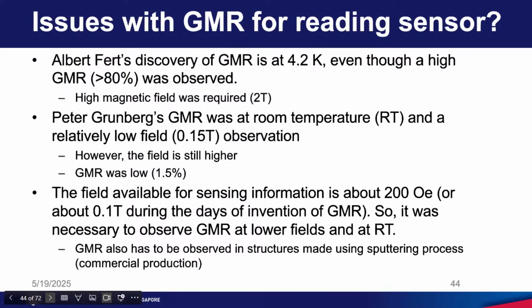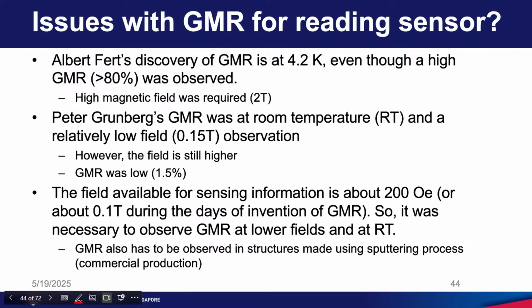So, what are the problems in the discovery? First of all, I told you that the work from the group of Albert Fert happened at 4.2 Kelvin. We are not operating a hard disk at 4.2 Kelvin, we are operating a hard disk at room temperature or at around 80 degrees Celsius. So this is one problem. This observation was at low temperature, and if you look at the result that I showed you before, the change between the high resistance and the low resistance happened at around 2 Tesla. You need a very huge electromagnet to produce 2 Tesla. Only then can you observe this high GMR.